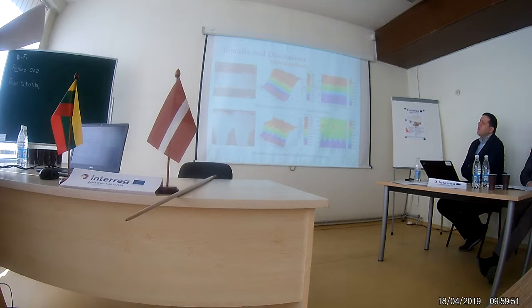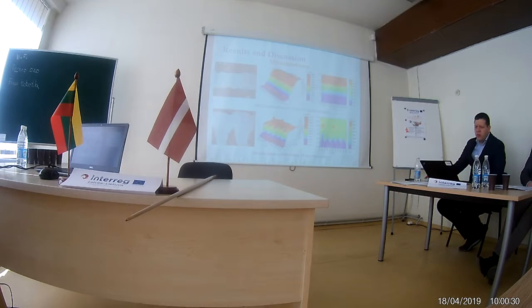So the analysis of microhardness distribution for both coating groups showed that the difference in laser-cladding methods had significant influence on the coating properties. These 3D graphs of microhardness distribution for both coating groups demonstrate microhardness distribution inside the coatings according to the average value of 5 layers of measurements.